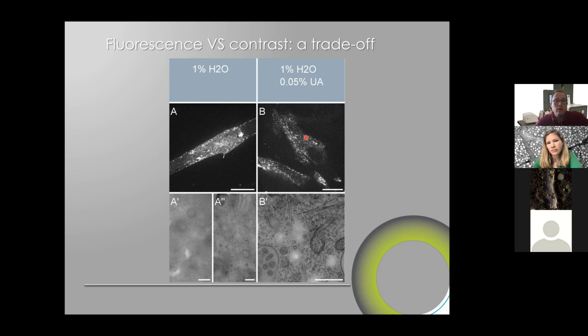And having no contrasting agent in the resin makes no contrast, and somehow it's charging the same way under the electron beam in SEM. So what we have to keep in mind is that the resin itself is not conductive, but in combination with a heavy metal salt, it starts to have conductive behavior. And one of the interpretations we have is that the resin behaves like a semiconductor. Semiconductors are molecules that are insulators, and as soon as you change the lattice and as soon as you change their native state, they become conductive. That's the behavior of a semiconductor. And that's really what it's reminiscent of looking at this behavior of the resin.